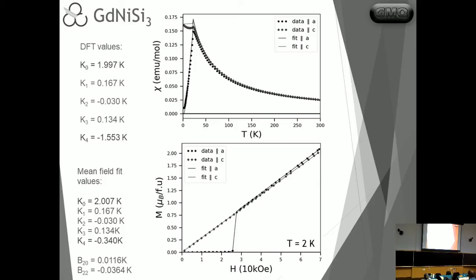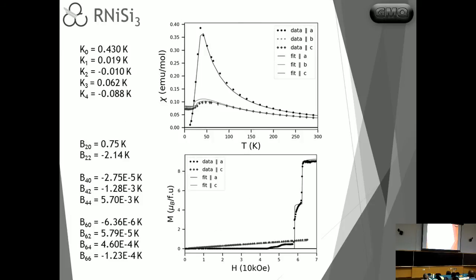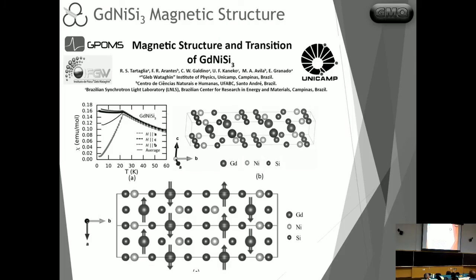So with magnetization versus temperature, the magnetic hysteresis, together with the metamagnetic transition, we can recover the low saturation moment or non-saturation moments of gadolinium in this case, all with the same sets of parameters, and also the specific heat, which is not shown here. Gadolinium is done. Terbium is also done. We can capture also these intermediate phases here, consistent also with the M versus T curves. So this is coming out well, and still needs to finish with the dysprosium and holmium, which is a little more complicated, but it's coming out nicely.